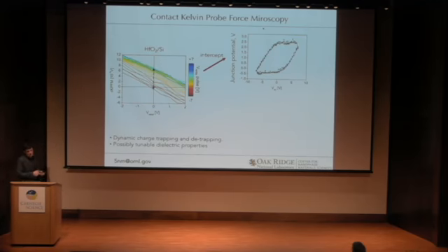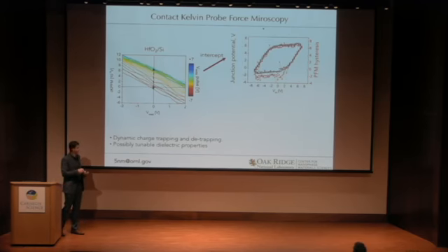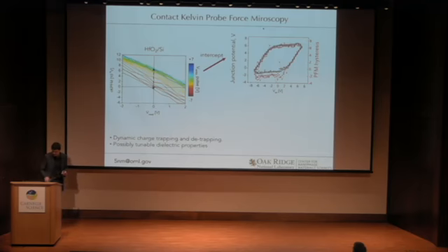And so this would correspond to a charge density of about over a few microcoulomb per centimeter squared. Interestingly, if you overlay this on a classic piezoelectric or PFM hysteresis, it will look almost identical once you scale them correctly. So we think we're on the right track.